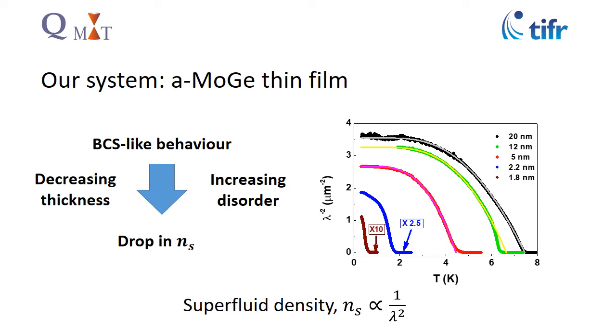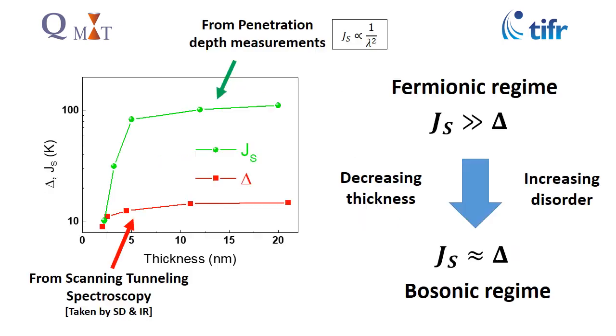Here you can see one of the results of the penetration depth measurements. The graphs are for different thicknesses. As you can see, for the higher thickness, that is the low disorder samples, it follows more or less the BCS-like behavior. But as we go to the lower thicknesses, it doesn't fit. And also there is a substantial drop in the superfluid density as we go to the lower thicknesses.